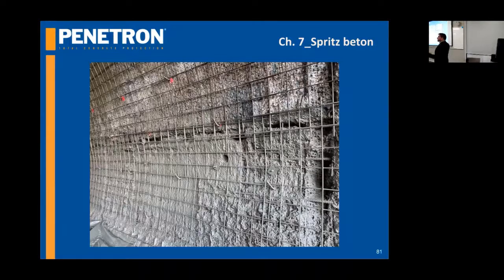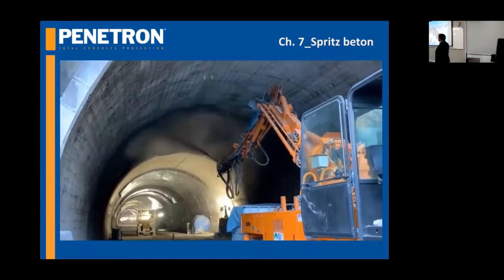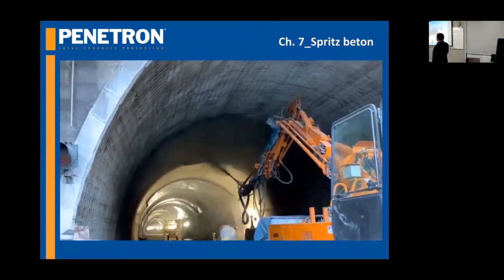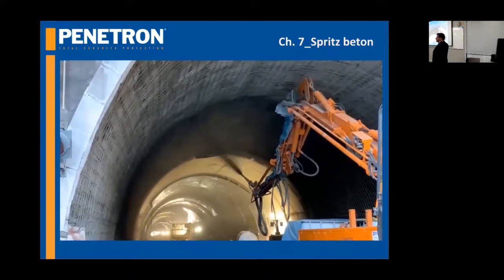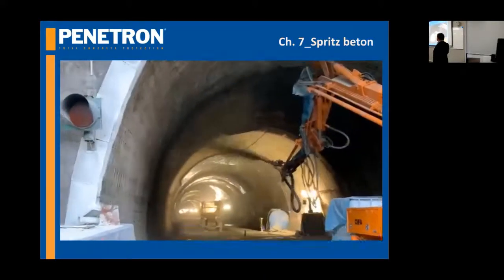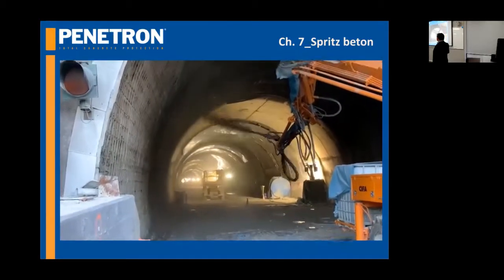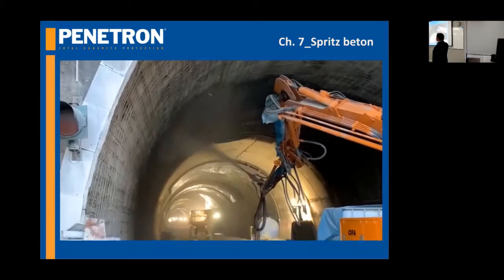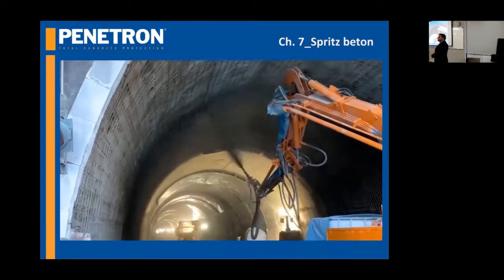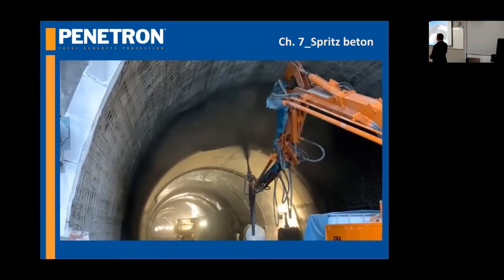The surface is ready for the bond connection between the new Penetron spritz beton and the old concrete, and then spritz beton with Penetron is being applied. This is a particular application, not an everyday solution, so it was nice to be seen. You can see also that there is little material wasted. Typically, when you use spritz beton, you get a lot of waste material because some pieces fall down and it doesn't attach a lot. With the Penetron Admix, we got very little waste material.